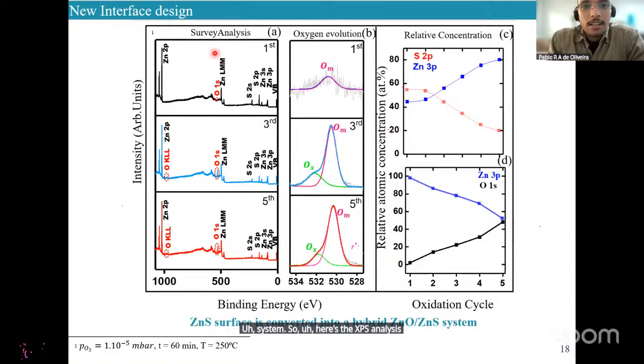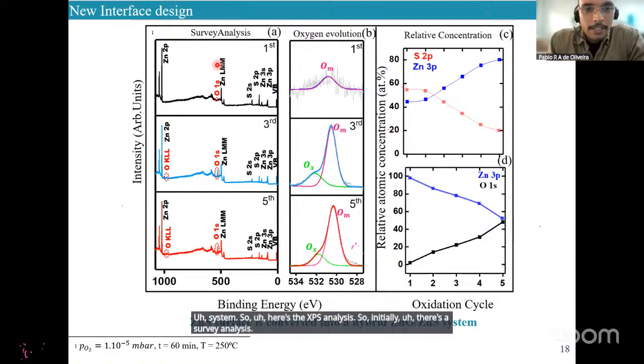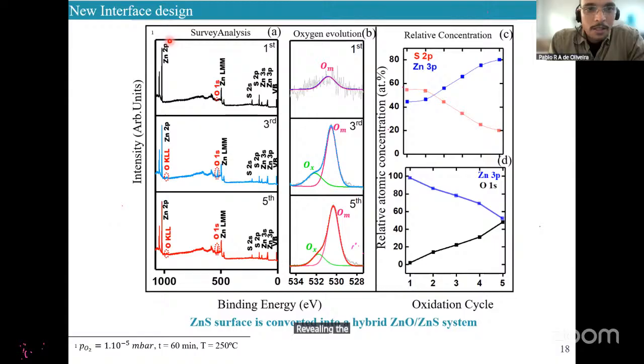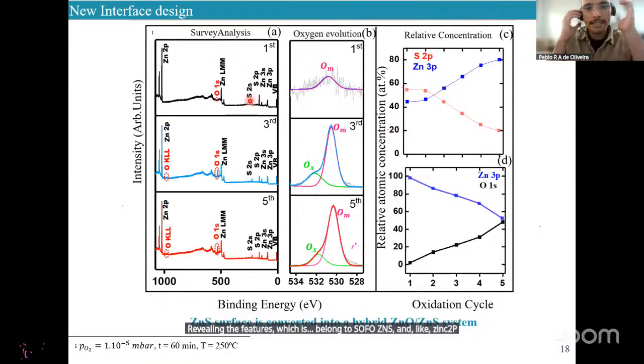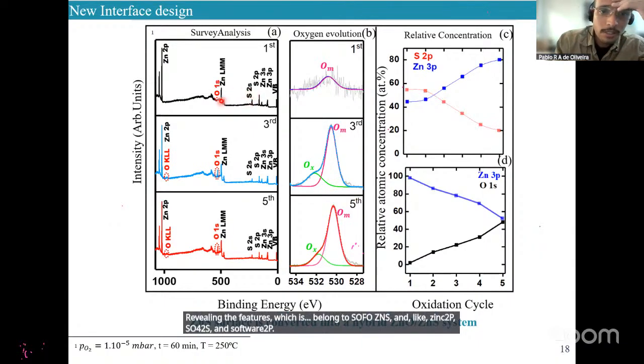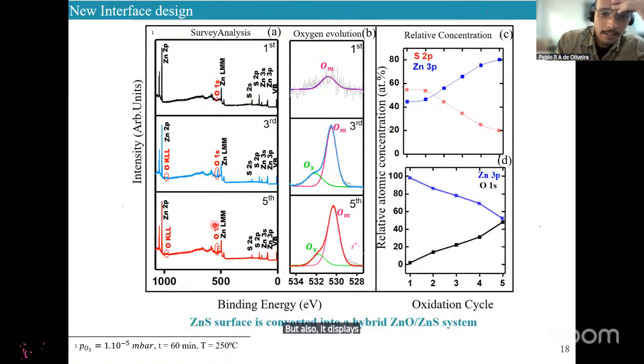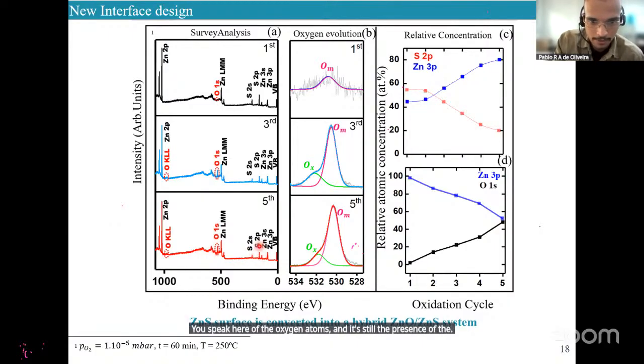Initially, this is the survey analysis revealing the features which belong to ZnS, like zinc 2p, sulfur 2s, and sulfur 2p. But it also displays oxygen features, especially after the 5 cycles of oxidation. We can note a huge peak of the oxygen atoms, and the sulfur features are still present, which might indicate the formation of a hybrid interface of ZnO and ZnS.